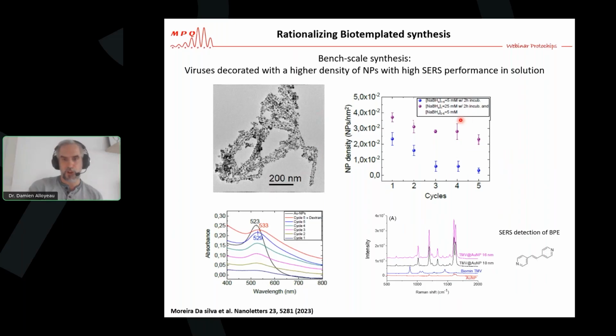And by applying this protocol on bench scale synthesis, my colleagues have been able to fabricate hybrid nanostructures with a density that is 10 times higher than if you are using reducing cycles with the same concentration of reducing agent. So that's what I mean by using in-situ TEM as a guideline. You can really improve your synthesis protocol just by observing it within the microscope. And here now we have this very interesting, very large absorption band, and those hybrid nanosystems are now used for SERS detection, and they have very interesting performance for SERS detection.